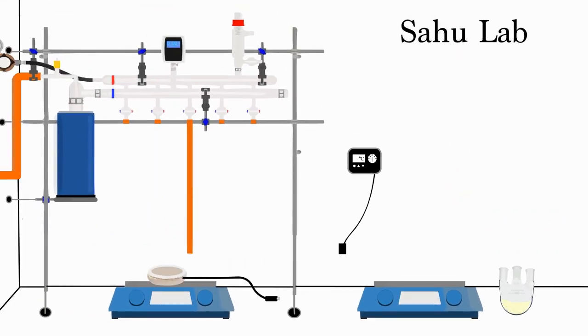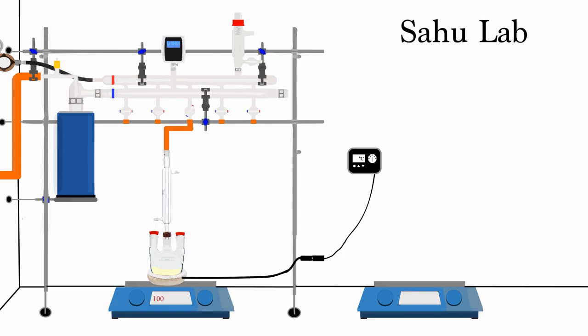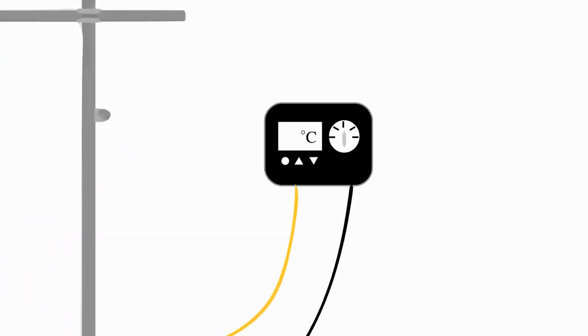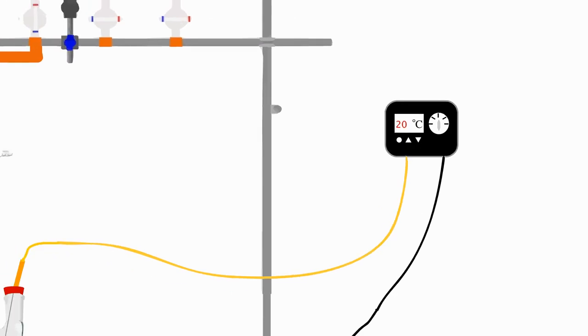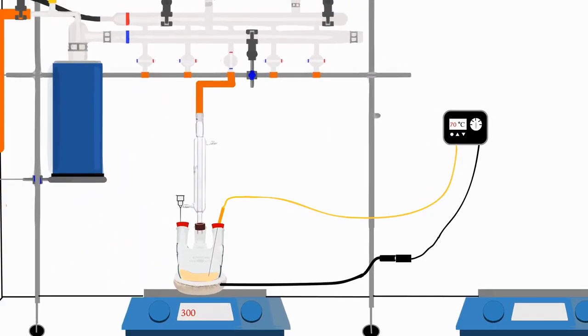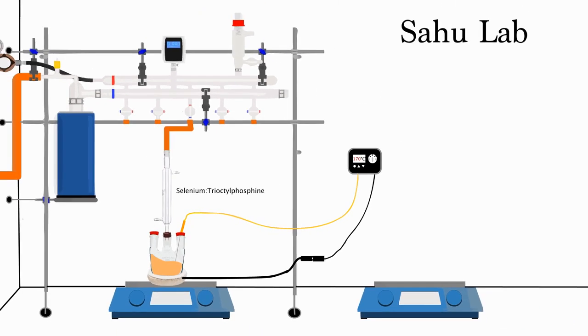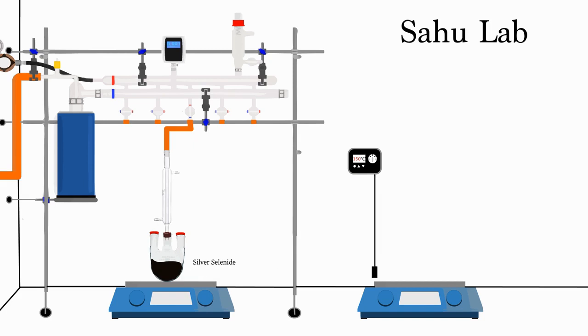This flask is then fitted with stoppers, attached to the gas line and placed into a heating mantle. Then the flask is flushed with nitrogen and the precursor is heated to 170 degrees Celsius, turning into a clear yellow liquid. Once it reaches this temperature, the selenium precursor is quickly injected into the flask. The new solution's color will change to a deep black and is stirred for an hour to form small particles.